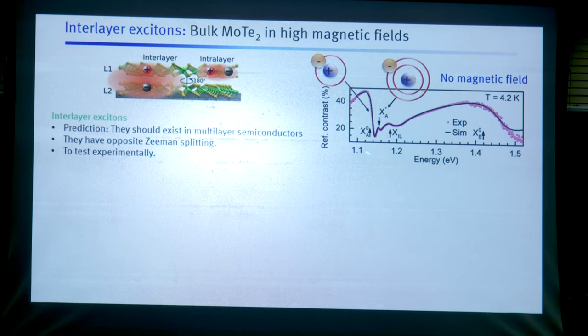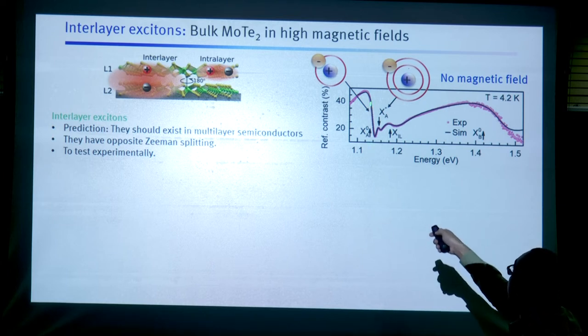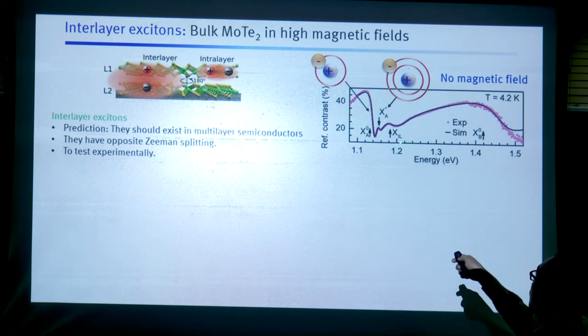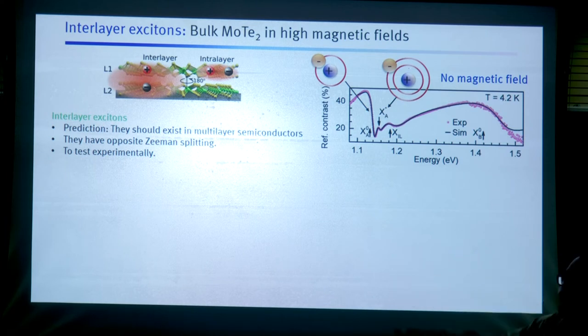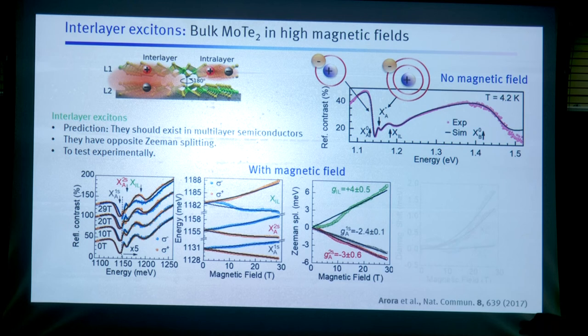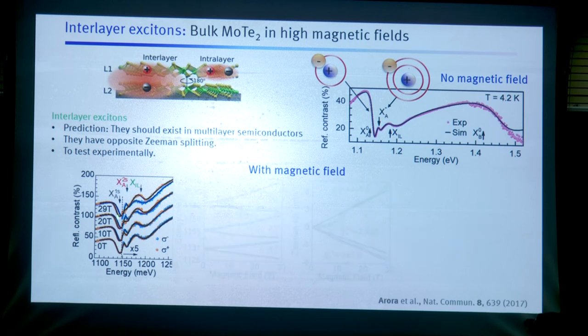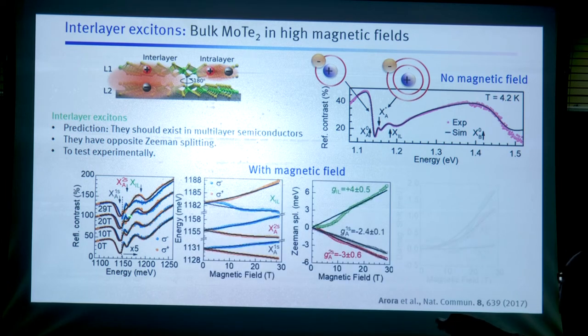Now this is bulk MoTe2. There is some peak here, there are two peaks here, and we have to see what these are. It turns out that this is a normal-looking intralayer exciton, and this is an interlayer exciton. I'll tell you how. We just apply magnetic fields and check their Zeeman effect. Here the Zeeman splitting turns out to be of the opposite sign to this one. If I plot their splitting separately, this third peak has a Zeeman splitting which is opposite to that of this peak. The g factor here is plus 4, here it's of the order of minus 3. Now this is a bulk material, which is why the g factor deviates from the value of minus 4, but it's still negative.